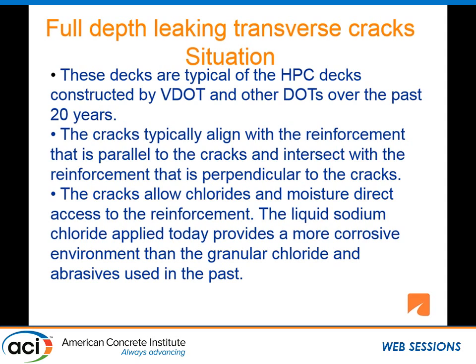The cracks allow chloride and moisture direct access to the reinforcement in the deck. Today, the liquid sodium chloride applied provides a more corrosive environment than the granular chloride and abrasives we used to use decades ago. We put down liquid today because it's so much more effective in preventing the formation of ice and snow. But at the same time, it's so much more effective in corroding the reinforcement and deteriorating the concrete.